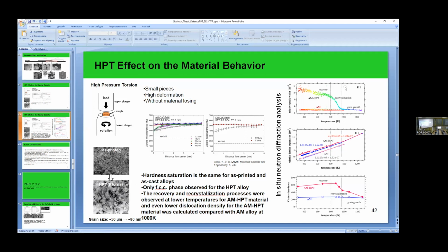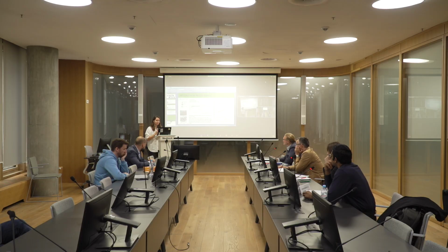Okay. And did you also look at the stress state during high pressure torsion? What is the stress state of the sample? Because you have a high pressure being applied, around 6 GPa, right? That's right. And you are doing these turnings, right? So what is the stress state it is subjected to? What is the stress distribution? Do you see it being homogeneous all around? Or do you see higher shear stresses compared to normal? Of course, normal stresses are not going to change the plastic deformation aspect. But where is the maximum shear stress that you observe? So like the shear stress along the cross section of the material.